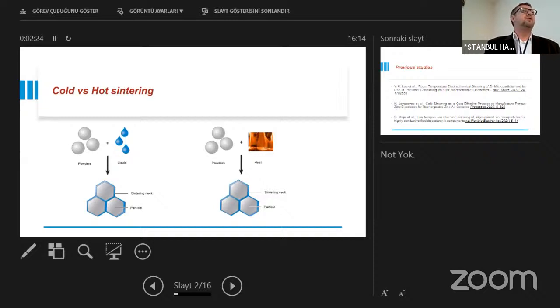This is based on a solution precipitation mechanism to transport materials from the particle to the sintering neck. In order to have this solution, you need some liquid, and to enhance this dissolution process, you need to apply pressure. For most ceramic materials, things are okay. But for metals, in order to enhance this dissolution, you need pressures that are impossible to obtain in an industrial way. In theory you can make tens or hundreds of gigapascals, but for practical application, there's no sense.